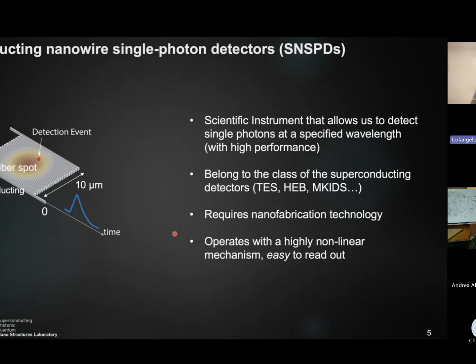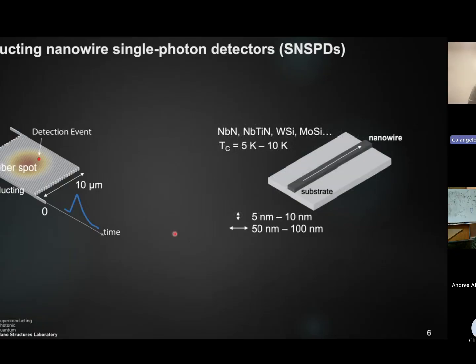So they're based on nanowires, so they do require nanofabrication technology. And the real thing is that this detector operates with a highly nonlinear mechanism, which makes them very easy to read out. Now, the nanowire is 5 to 10 nanometer thick, 50 to 100 nanometer wide, and it's made of type 2 superconductors, for example, niobium nitride or niobium titanium nitride, which has a critical temperature between 5 to 10 Kelvin. So effectively, this is a cryotechnology that needs to be cooled down.